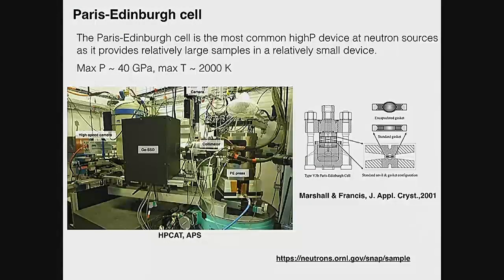The Paris-Edinburgh cell is something somewhat in between. It's most popular for neutron science. It's of this size roughly. So it allows, without the size of a multi-anvil large volume press, to achieve quite large sample volumes. Indeed, it can also be cooled at the very least to liquid nitrogen temperatures, but I also think below. It has tungsten carbide anvils for the most part, but they are also starting to use sintered nanocrystalline diamonds as well.